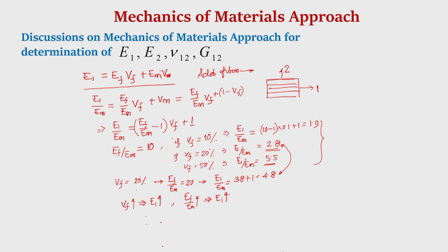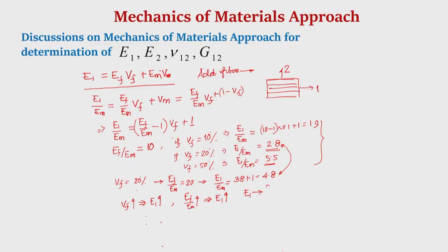What we observe is that as V_F increases it has a significant effect on increasing the longitudinal Young's modulus. For a given V_F, as E_F/E_M increases there is also a significant increase in E_1. The fibers, both in terms of their modulus and their volume fraction, significantly influence E_1; therefore E_1 is a fiber-dominated property. Next, let us understand the load-carrying capacity and how addition of fibers influences the stress-strain relationship of a composite.